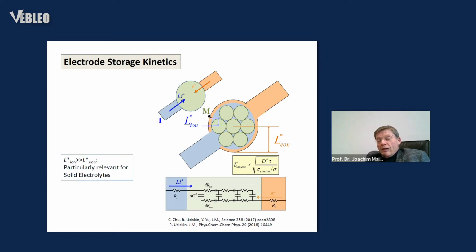This is very important. So you have a powder agglomerate here, and here we have electrode particles which we assume are good electron conductors. So if this is so, then you can be pretty relaxed with your electronic contact. So it can be far away from the middle, the next electronic contact. We call it an electronic wiring length, can be far away. But not so for the ion contact. This mesh size, so to speak, has to be very small. So knowing this, a simple consequence would be you can spare a lot of graphite that you normally have to add.